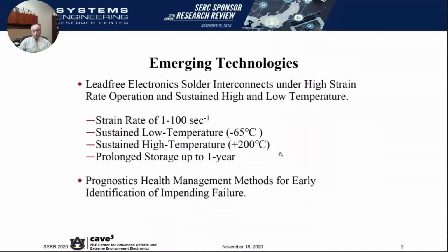And in the harsh environment applications, much of the electronics may be subjected to strain rates in the range of 1 to 100 per second and sustained low temperature down to negative 65 degrees centigrade, sustained high temperature up to plus 200 degrees centigrade, and prolonged storage up to 1 year. A second subtask deals with prognostic health management methods and the development of early indicators for identification of impending failure. Both subtasks are responsive to the ability to mitigate risk with usage of these newer interconnect technologies, newer materials that have entered this particular interconnect space.